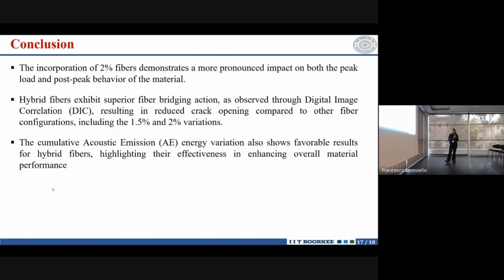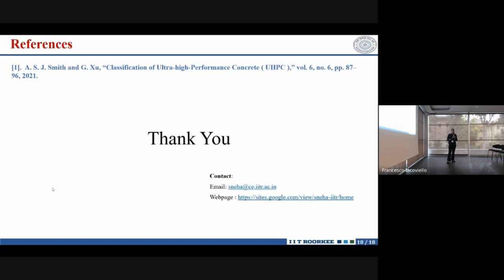So if we conclude my work, if we just see the load CMOD results, we can say that 2% fiber is behaving well. But if we are concerned about the crack mechanism, crack propagation, where crack length and width are important, and we don't want the crack to open wide very easily, we have to go for the hybrid combination, and it is performing better in the way the crack is propagating in the material.